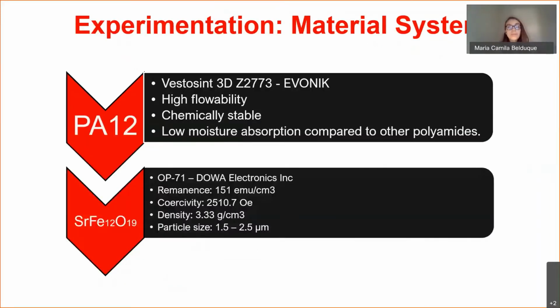Okay, so we're going to use two types of materials in this study. They are nylon 12 powder from Evonik because of its high flowability and chemical stability. This indicates a good capacity to be mixed with other materials and provide a good adhesion. Additionally, it has a low moisture absorption compared to other polyamides.